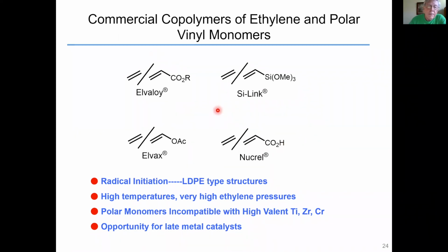The early metal systems are incompatible with these polar functional groups. So these systems are generally made through radical initiation. And so you get low density polyethylene type structures, highly branched structures. Now, one of the problems, or the couple problems here: one, this requires extremely high temperatures and very high ethylene pressures. Two, you don't really have much control of the microstructure. You kind of take what you get here.